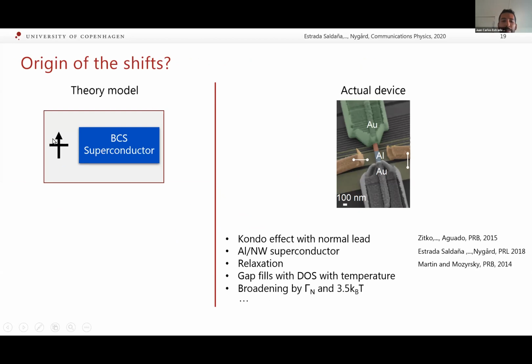So the theory model is a spin coupled to a BCS superconductor. The actual device, we're studying it in transport. We're studying YSR states in transport. This was a spectral function calculation. And in the transport, we have to add a normal lead. And this lead can lead to a Kondo effect, even though we don't observe any zero bias peaks in our data, which could prove that this is the case, this might still be happening. The temperature might just be smearing the Kondo effect.